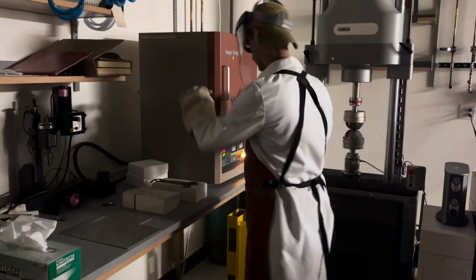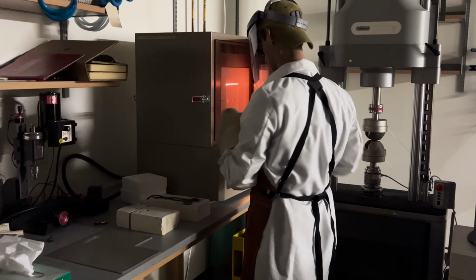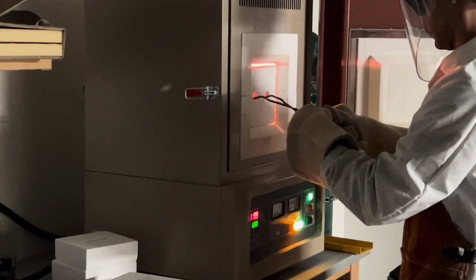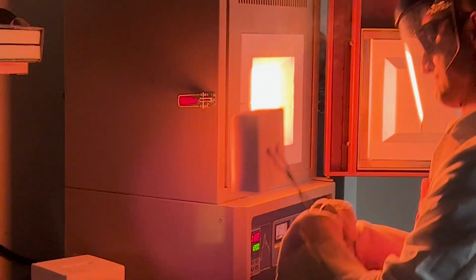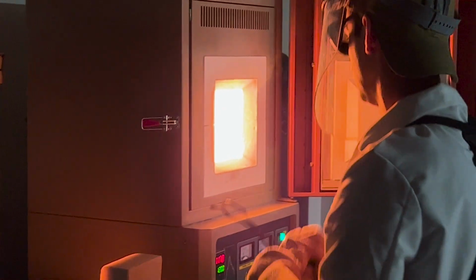The invention is a high-temperature refractory alloy, ternary of molybdenum, chromium, aluminum, the development of which started with my personal interest in hypersonic aircraft and jet propulsion. So we started the development of this alloy looking at molybdenum alloys, and then we picked 6 or 7 alloys across the phase diagram, and it turns out the one that worked was actually chromium-rich, so we ended up flipping the script a little bit.